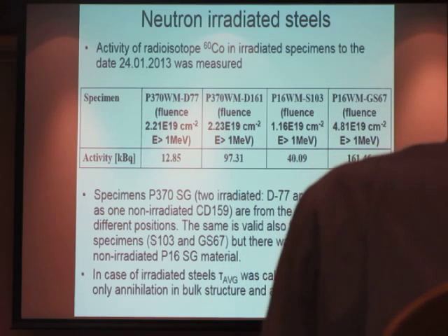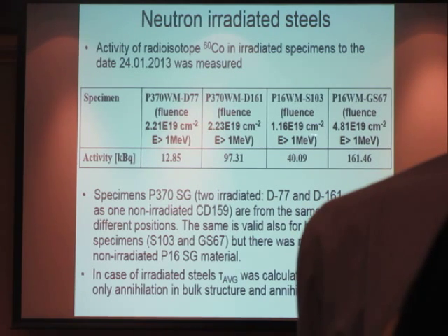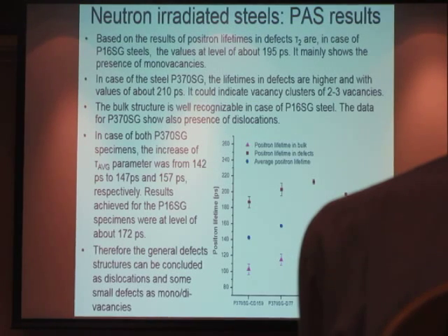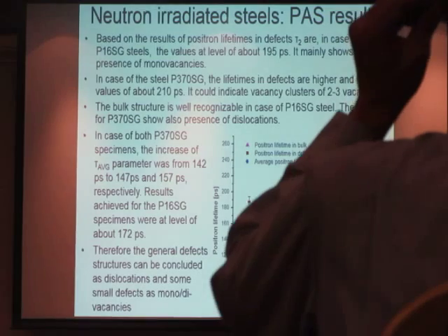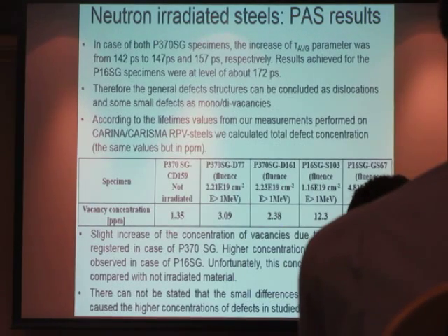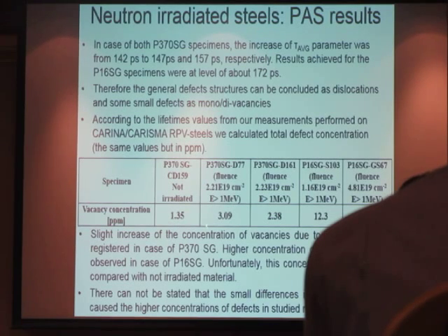important messages. We had the original and neutron irradiated specimens on this level, then 10^19 cm^-2 as well. It means that it's really at the level of 0.1, 0.15 dpa at maximum. We measured it by a 3-detector setup. There are some results. We see also two-component analysis, and we also calculated the concentration of the defects in the material. In this material, P16 weld metal, it was higher than the other one. Nevertheless, the not irradiated level was at 1. So in each material at the beginning you have enough defects.